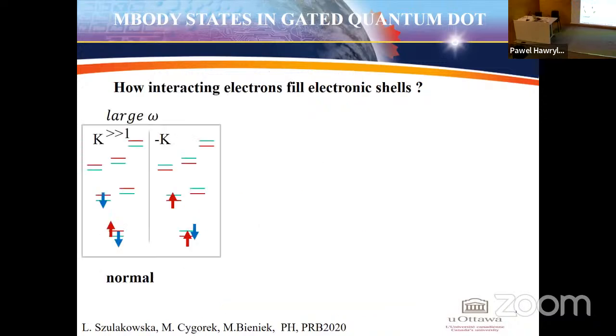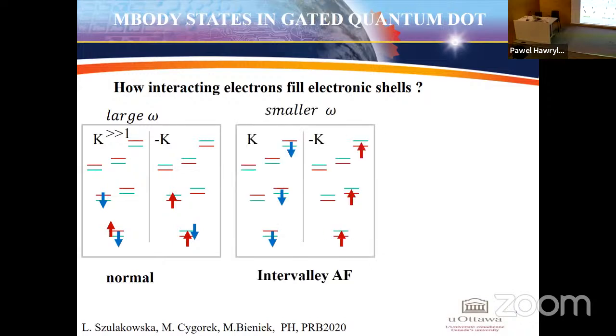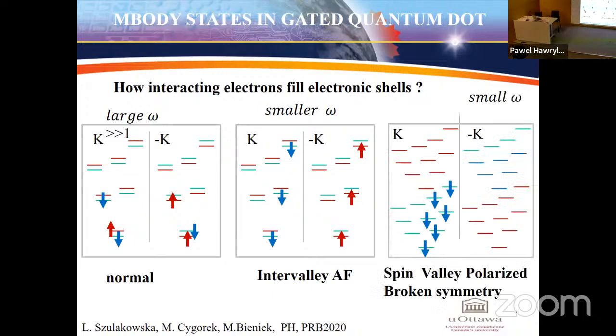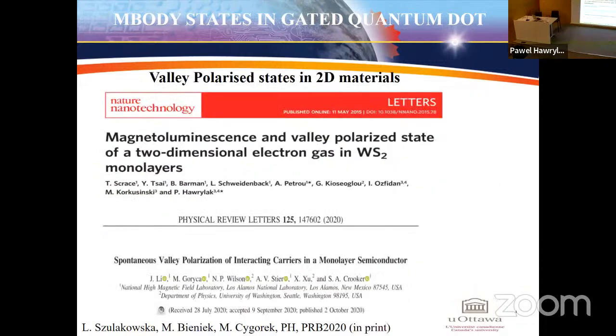And now we can answer the question of how electrons fill electronic shells. So at large omega, they just feel it normally, so they minimize the kinetic energy. When Coulomb interactions start to play a more significant role, we find an intervalley antiferromagnetic phase. So you have a spin polarized state in one valley and an oppositely spin polarized state in the non-equivalent valley. And then at very strong interactions, we find spin and valley polarized broken symmetry states. And that is something that we think we have seen before in magnetoluminescence experiments on tungsten disulfide, where I think the valley polarized state of a two-dimensional electron gas was seen.